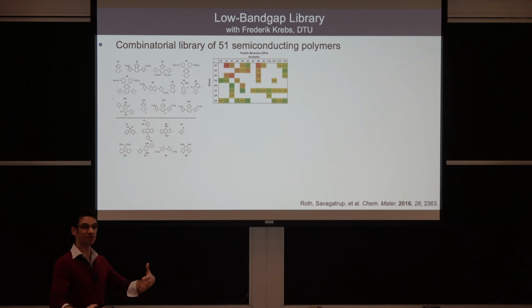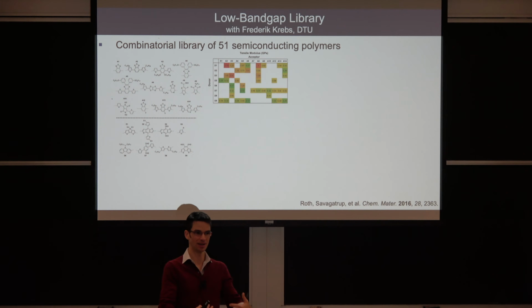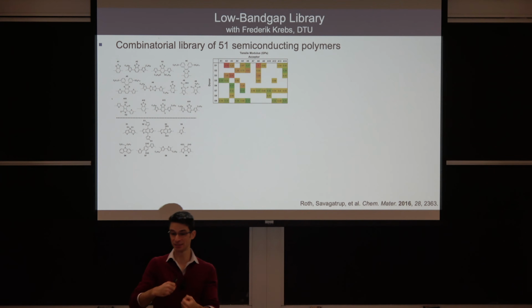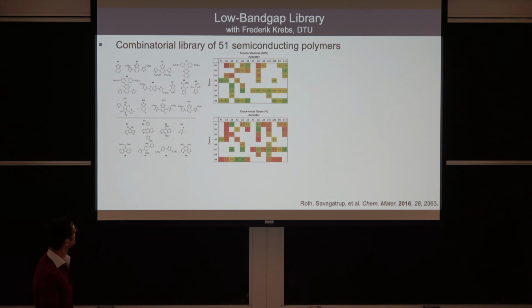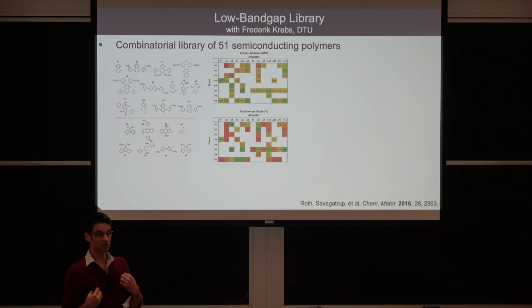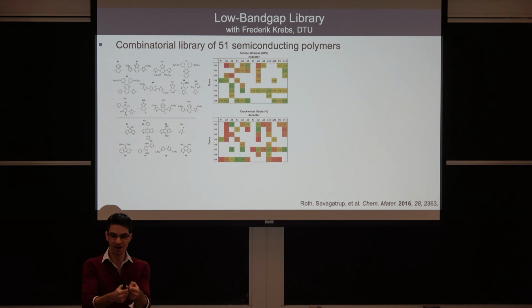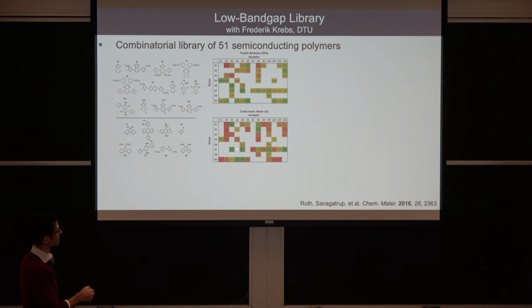That's because if you have a softer material, lower tensile modulus, it might tend to give you less interfacial stress with other layers in the device, and the device might survive easier. This is the crack onset strain, which is kind of like the equivalent of the strain at fracture, except that we're doing these on silicone rubber substrates because the materials are so thin. So what you do is you stretch it out. As soon as it cracks, you mark that down in your notebook. So the higher the number here, 68% strain, that's pretty good for a semiconducting material. Try doing that to a silicon chip.